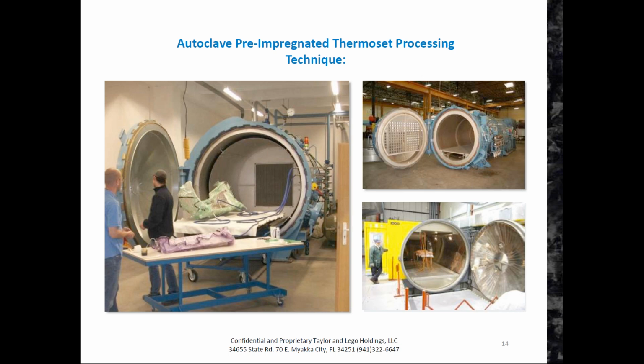It still gets vacuum bagged, and the vacuum bagging process outside the autoclave is done really to massage everything into place. It's still only 1 atmosphere of pressure on the outside of the autoclave, but once it goes into the autoclave, you can apply about 10 atmospheres of pressure. So let's just say about 150 psi in total. It's literally 10 times the pressure on the part, so your thicknesses tend to be more uniform. But because it is still low pressure comparatively to the other processes I'm going to get into later, you still have some reasonably significant variation in thickness.